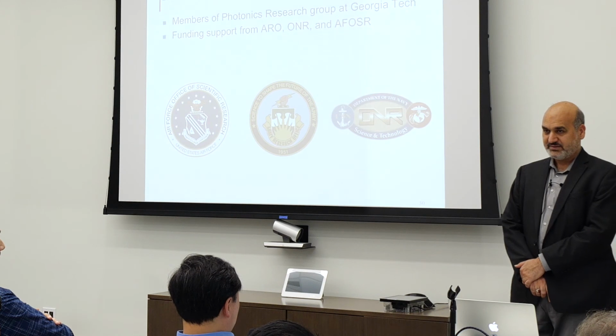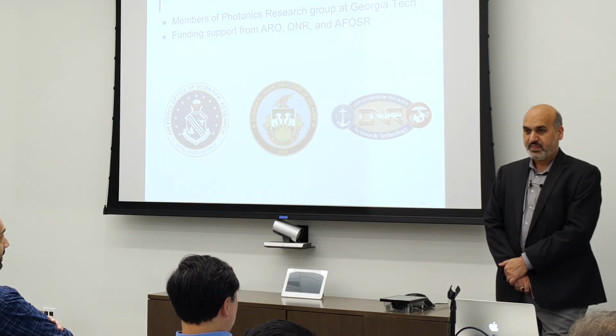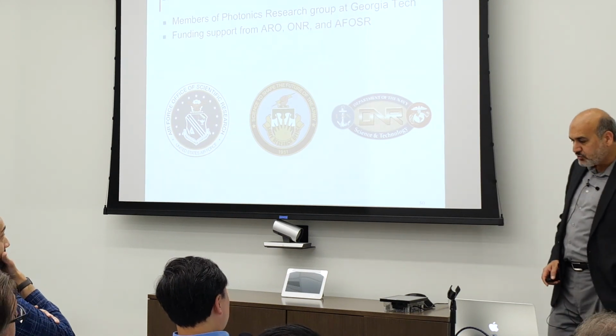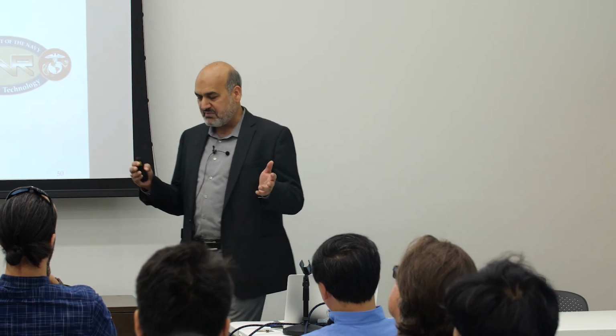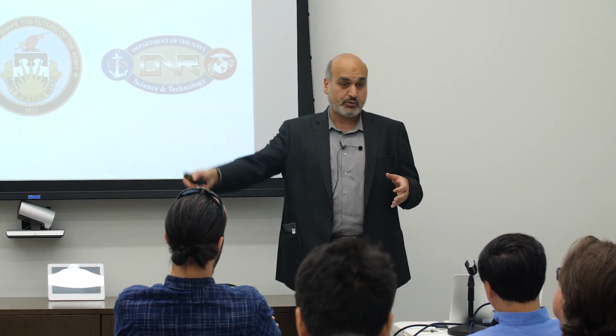I'm a semiconductor process guy. So the geometry is basically 20 micron, something like that. The geometry of the fabrication process, yes. Well, the resonators are usually somewhere between 1.5 to 2 micron in radius. They could go all the way to 100 micron if we want to really push the quality factor.